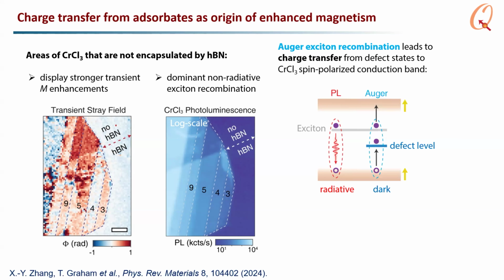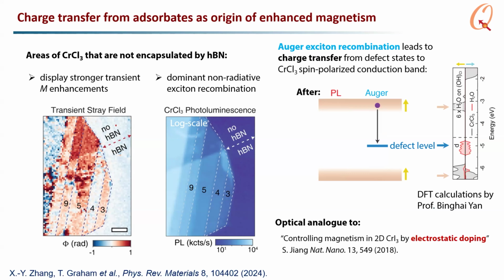Our proposal for this effect is that we have an Auger recombination of the excitons. Normally the excitons, an electron hole pair, just recombine with each other and give off a photon. But if you have a defect state within the band gap, that energy can be given off to the defect state, promoting it to the conduction band, which in this material is spin polarized. That can lead to optical doping of the material, which leads to an enhanced magnetization.